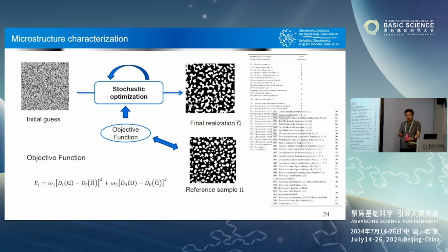So how did we do the reconstruction to ensure we capture only the chosen descriptor and nothing else? The process is simple. We start with a random guess. It could be a Gaussian distribution, and then we have our target. Each time we try to swap the pixels, and after each swap, we check if this swap makes us closer to that target, measured by a loss function, which is defined by that chosen descriptor. We continue that iterative process until it converges. The loss function keeps getting smaller and smaller until it reaches the threshold. At that point, we end up with a final realization, which contains just that information, no more, no less, measured by that particular loss function, which is that particular descriptor.